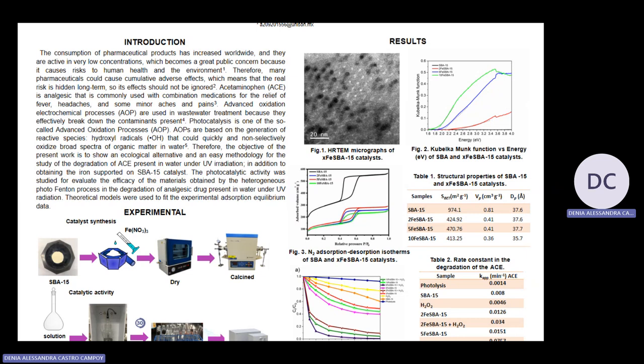Table 1 shows the structural properties of the catalysts. The specific surface area was determined using the BET equation, and the pore volume and pore size distribution were determined by the Barrett-Joyner-Halenda (BJH) equation. This table shows a decrease in specific surface area and pore volume of the support due to the incorporation of iron, resulting from blocking of the mesoporous channels with iron oxide. However, in the 5%-iron SBA-15 sample, the structural properties increase.